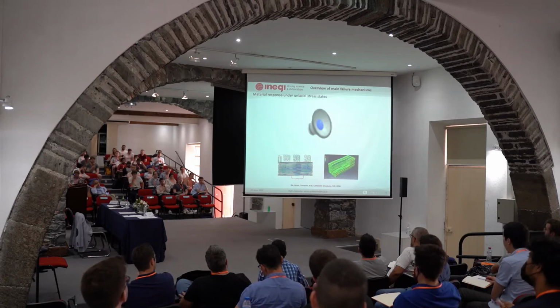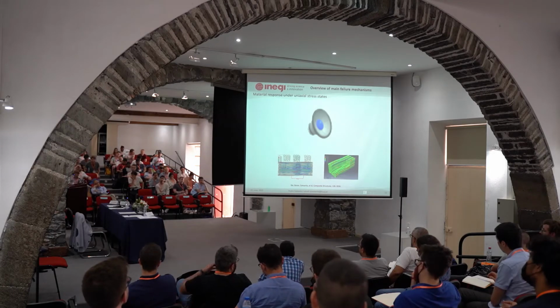Previous page. Yeah. Before that. This one. Yeah. And if you calculate the compression modulus, which strain data are you using for ductile failure? Well, what you can do is from the final model. So we're talking about the compressive modulus. We are in the linear regime, right? So it's very easy to homogenize. So you can get stresses, you can get strains, and for that you get elastic properties.